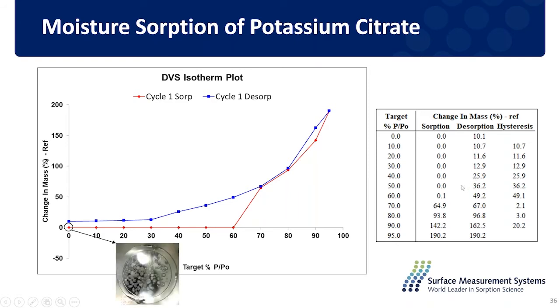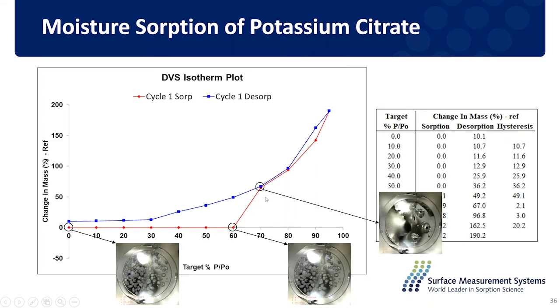And we also took some photo images while running this experiment. So you see at dry condition it is a granule sample. It's the same at 60% because there is no uptake of water. And when it starts picking up moisture, it partially dissolves at the beginning of 70%. And then it's fully dissolved at 90% or 95%.